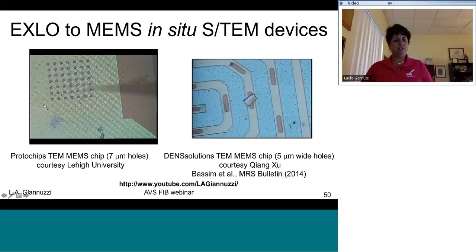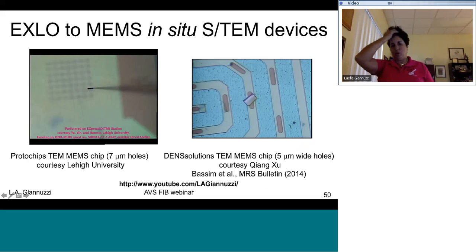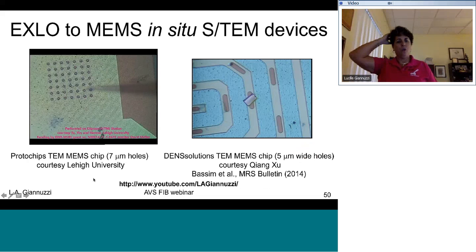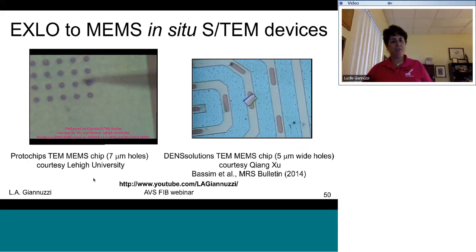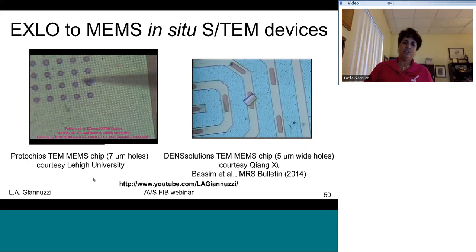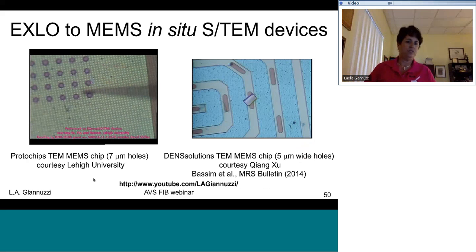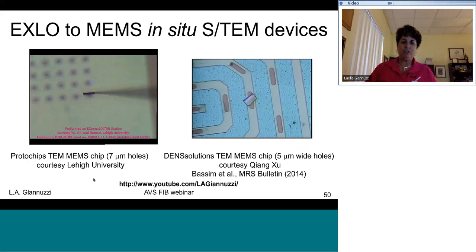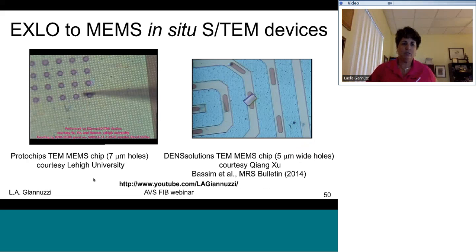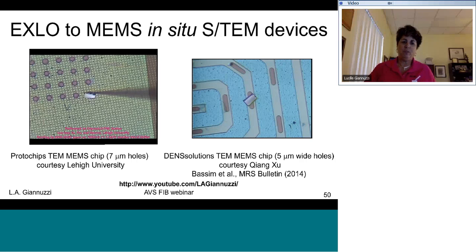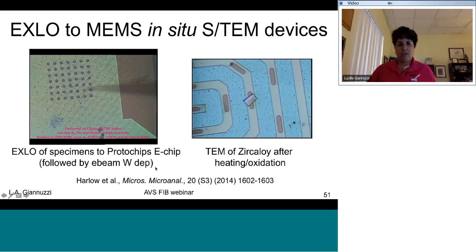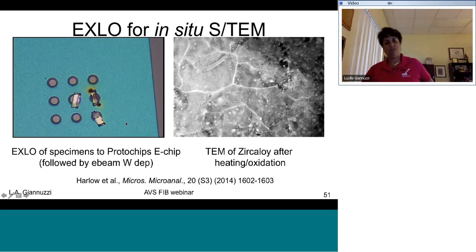Okay, this technique turns out to be actually perfect for doing in-situ TEM, where it's required to get an electron transparent specimen on these various MEMS devices that are made by various vendors, such as Protochips, DENSsolutions, etc. So for these in-situ MEMS devices, you need to get an electron transparent specimen onto the grid, and it turns out this is the perfect way to do it without FIB damaging your sample via FIB imaging in-situ. And here's some additional work by the group at Drexel showing